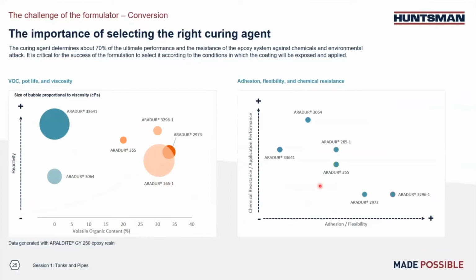And if we look at the chart on the right side, we list chemical resistance and application performance, and on the x-axis is adhesion and flexibility. You can see ARADUR 3064 has overall pretty good chemical resistance. And chemical resistance a lot of times can be complicated, right? Maybe some hardener is very good in the solvent and maybe not very good in the caustic. And some maybe is very good in the acid, but maybe not very good in some chemical tests, right? So you always want to pick the right curing agent or combination for your end needs, right?